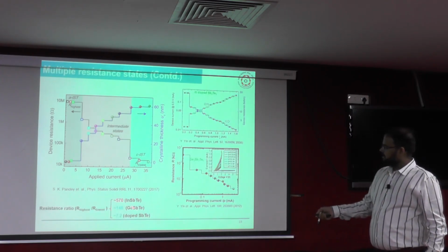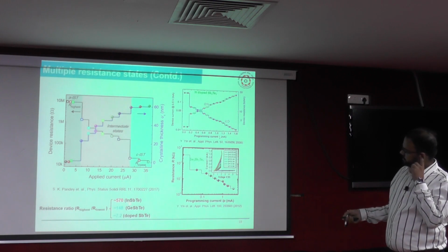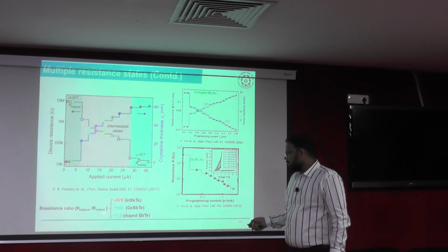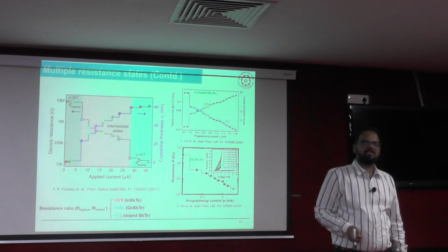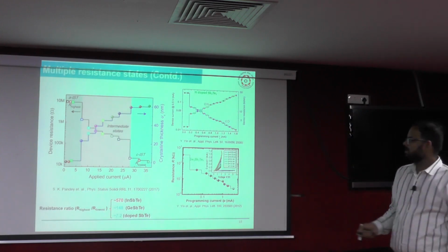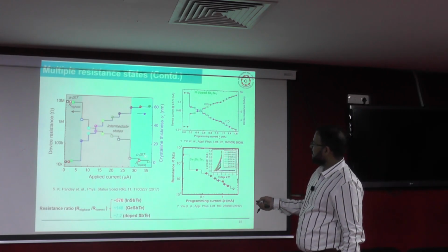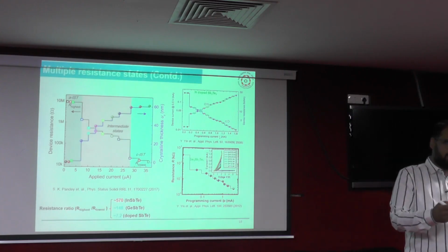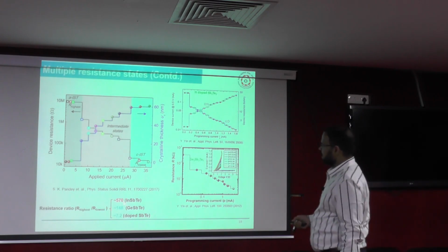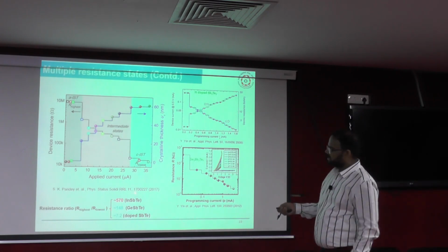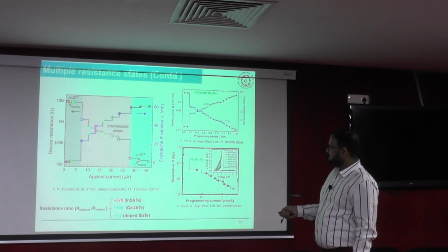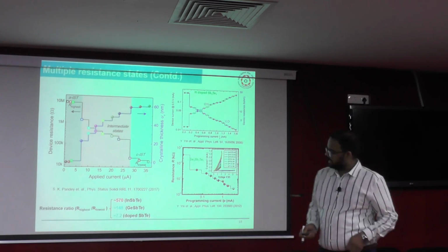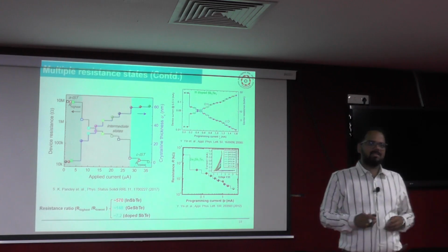This IST is compared with GST and doped SBT. So you know what is the important thing in this case? The on and off ratio reported in this case is on the higher side. It is around 570, from R highest to R lowest. If it is on the higher side, then yes, we can use this material for further application and we can test it for multi-level applications. And it is reported for the same programming scheme for GST it is around 148, and for doped SBT it is 7.2. So in both cases it is much higher.